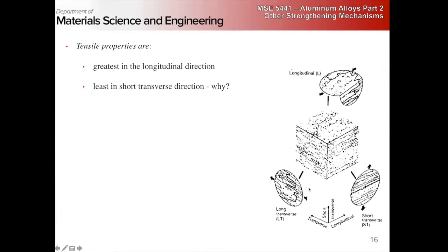It's going to be least in the transverse direction, because now we have a whole bunch of parallel plates of these intermetallics that I'm pulling orthogonal to. So I can easily crack, and now I'm pulling parallel to crack faces, which is okay, except I've got a whole layer of cracks. If I'm pulling longitudinally, I don't have a whole layer, I have a strip of cracks.